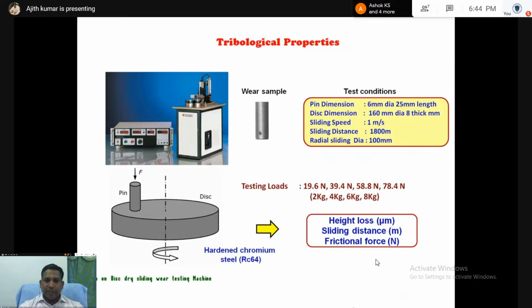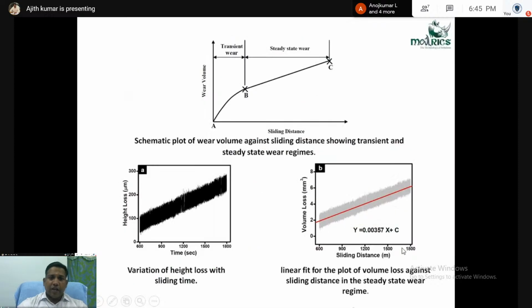tribological property. This is a tribological sample, 6 mm diameter to 12 mm diameter samples we can use. The length is about 25 mm. This is the pin on disc testing setup. From that pin on disc testing setup, we can get the data of height loss, sliding distance, and frictional forces. So from this data, we are analyzing how the wear property is changing.